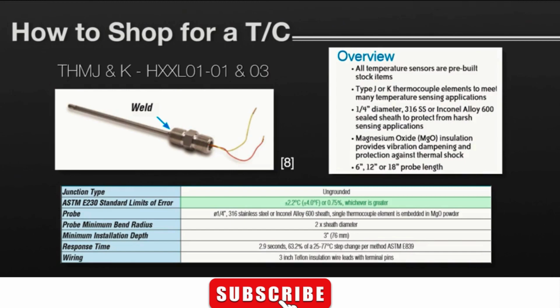This means that at temperatures lower than 293 degrees C, you will always have an error in your reading up to 2.2 degrees C. And above 293 degrees C, your error will be up to that 0.75% of whatever temperature you're actually measuring.